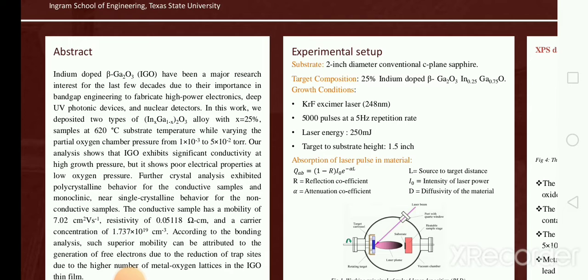We found that our sample shows conductivity at high oxygen pressure, while at low oxygen pressure the sample is non-conductive. From the crystal analysis, we got polycrystallinity at high oxygen pressure, whereas our sample is close to single crystallinity at low oxygen pressure.